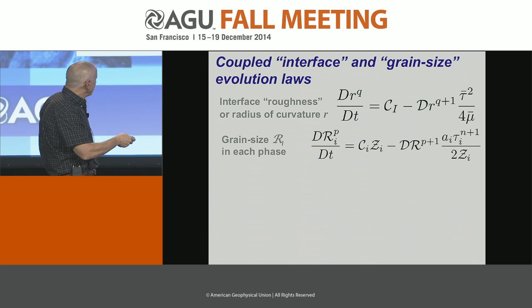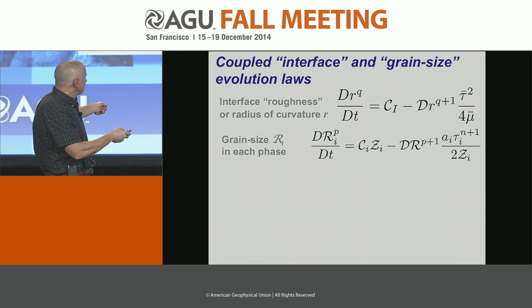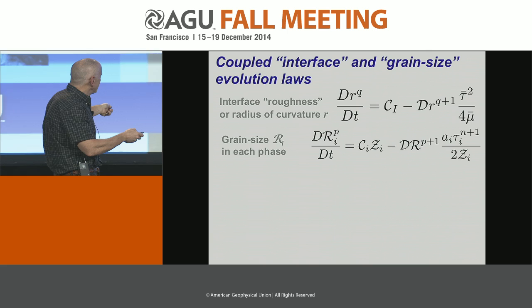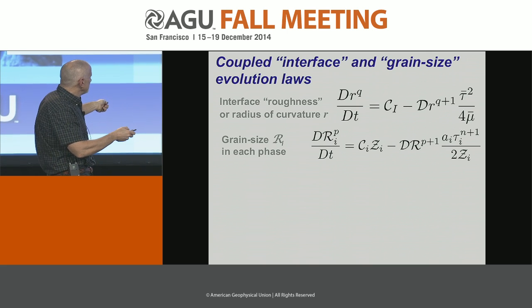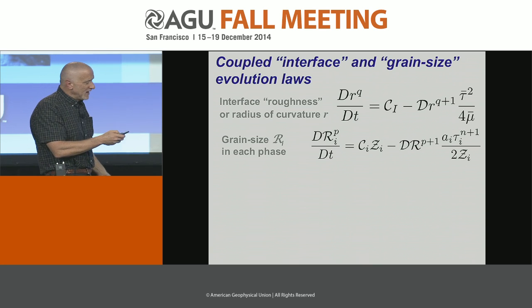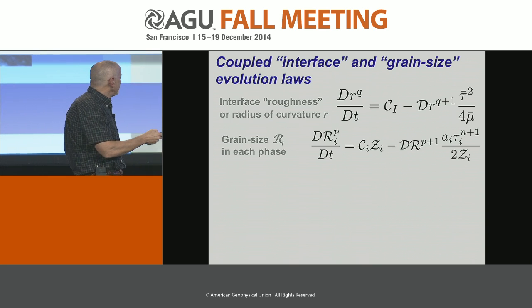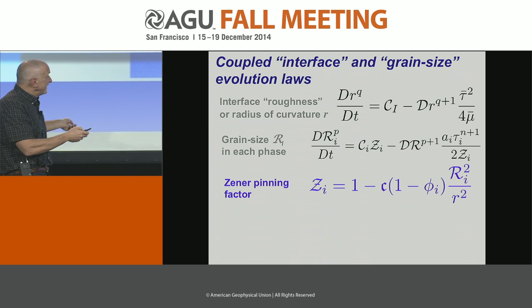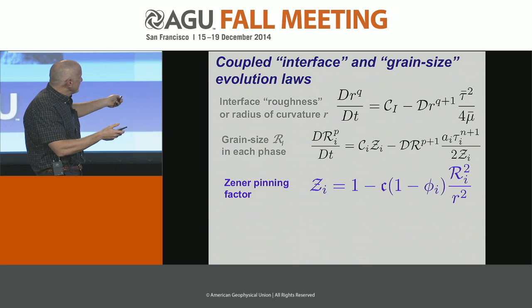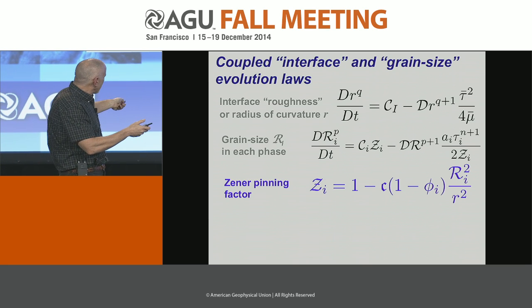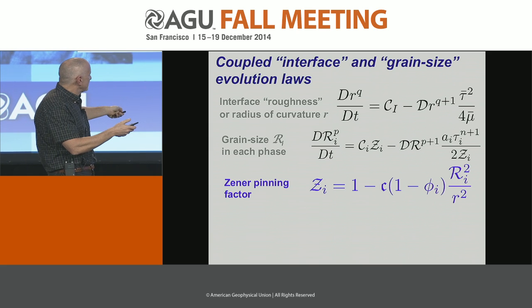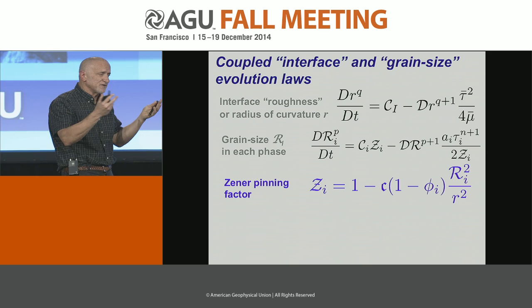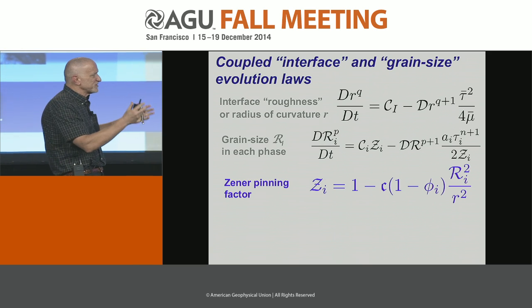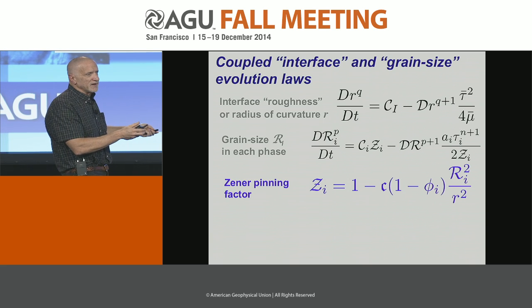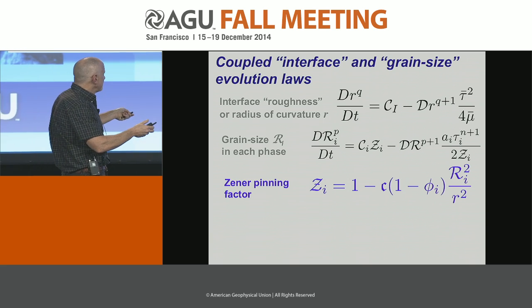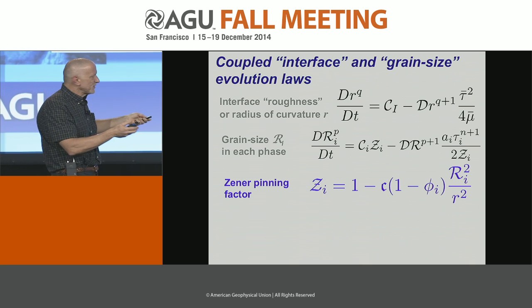Likewise, we have very similar laws for the grain sizes. This I means either olivine or pyroxene for either phase. Similarly, there's a competition between coarsening and the damage. But they're coupled with it by this thing called the Zener pinning factor. And the Zener pinning factor is something that drops out rather nicely from all the thermodynamics that you had to grind through, but it basically states that for very small grains, maybe separated by large smooth interface, you will get really no pinning. So in that sense, this ratio would be very small, and the Z is 1, and it just undergoes normal coarsening.